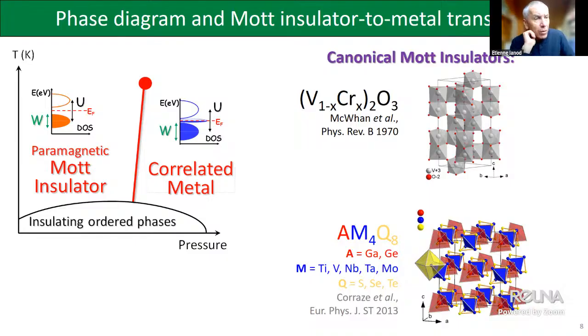I can imagine, but maybe one thing about perovskite. In perovskite, you tune the bandwidth usually by tuning the rotation of the octahedra, and in most cases it's there. It's not the only reason, but it's one of them. What we are doing here, we have no sign that we are manipulating the degrees of freedom inside of the unit cell. Here, the effect is more the compression of the unit cell. You see what happened, and if you keep the same geometry but you compress the volume, still you will increase the bandwidth.